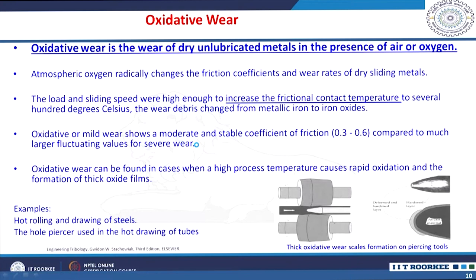Regarding oxidative wear, it is the wear of dry unlubricated materials in the presence of air or oxygen. So, atmospheric oxygen radically changes the friction and wear rates of the dry sliding materials. Again, the parameters of the sliding, such as loading and sliding speed, if they are high enough, then they increase the frictional contact temperature to several hundreds of degrees Celsius, and the wear debris changes from metal to metal oxides, right. So, you will see several examples where metal becomes metal oxides in such high contact temperature conditions, because of the friction.